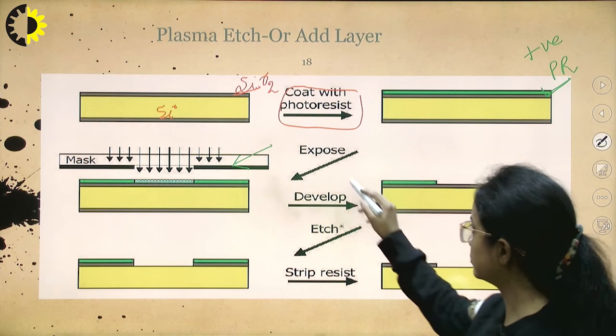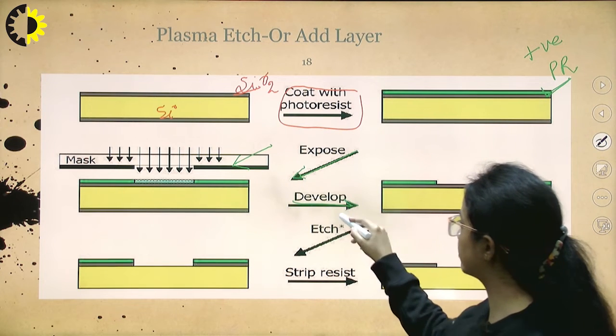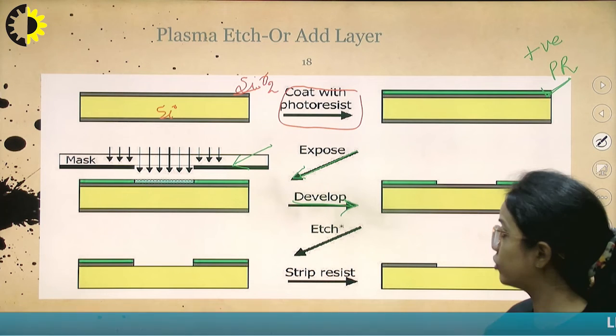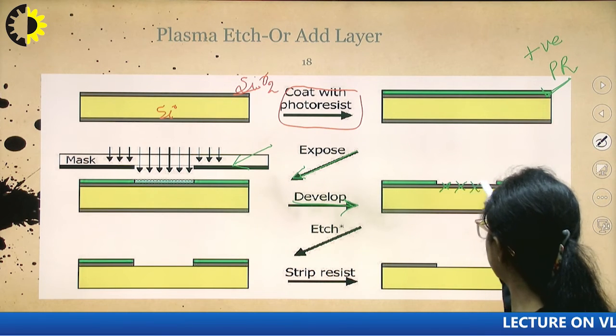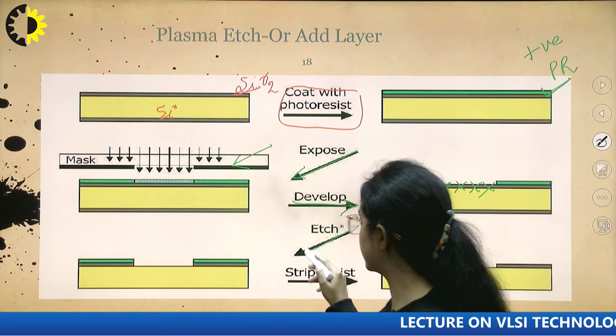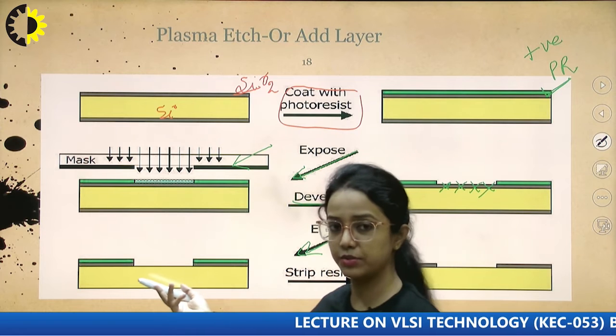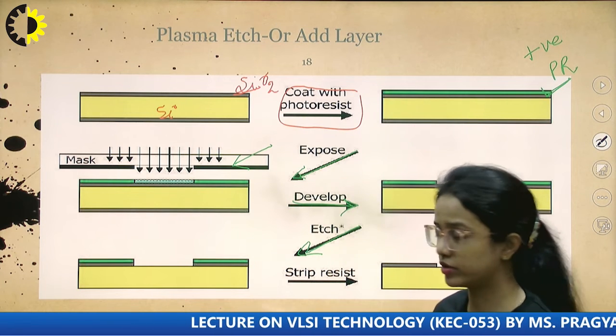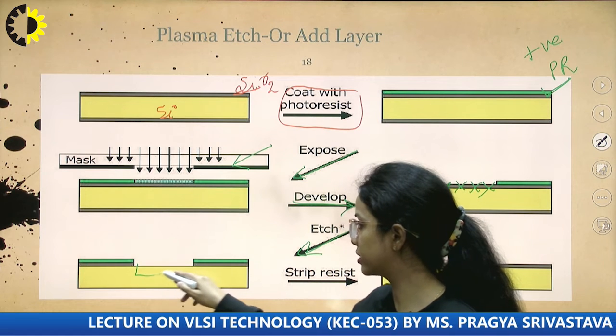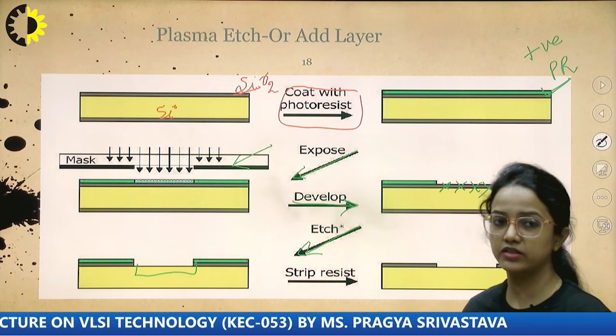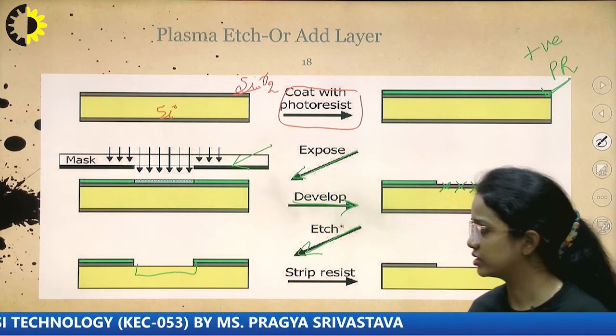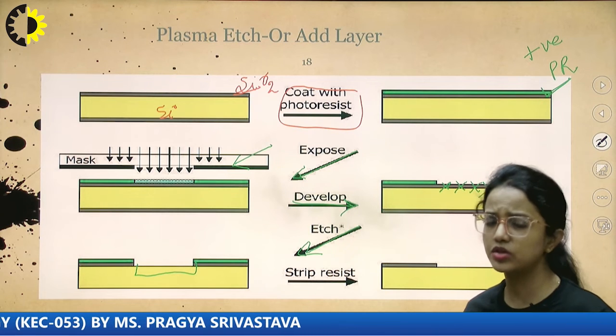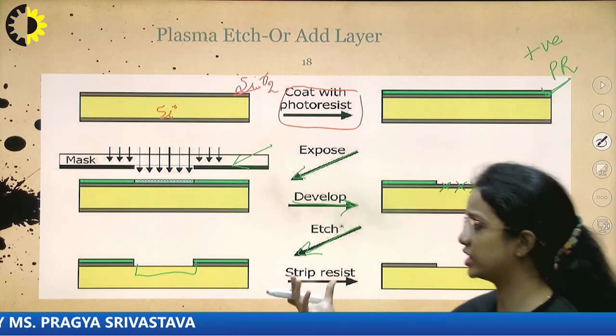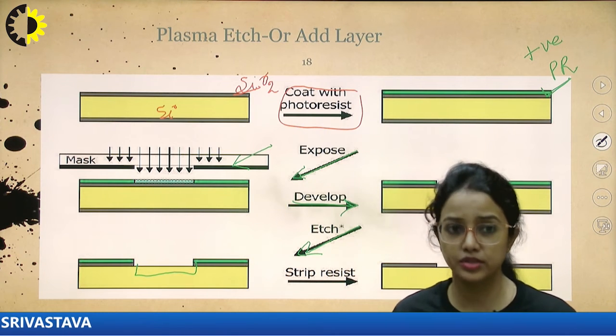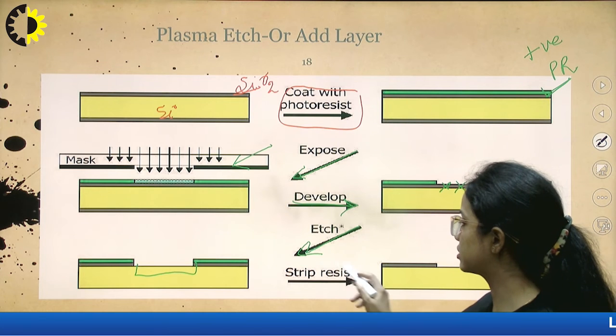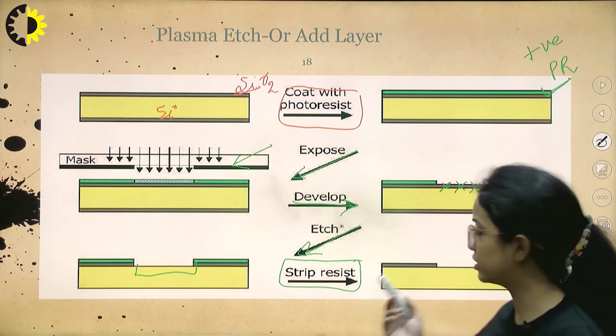Now this was exposure. After developing, we have seen that the exposed portion has been washed off. Now to remove this unwanted layer of SiO2, we have performed etching. This etching will help us in removing the unwanted layer of SiO2. So here is the place where we can create an N well. But now we do not need this layer of photoresist, because we have created a well-defined boundary. Since the boundary is created, we don't need this. So we will just strip the photoresist, and here is the required